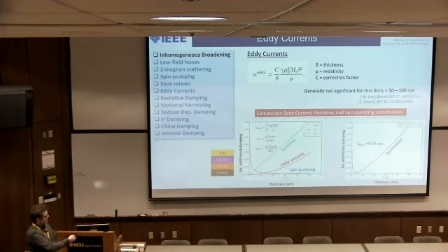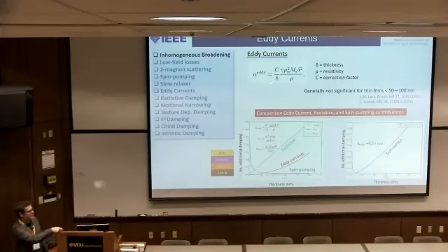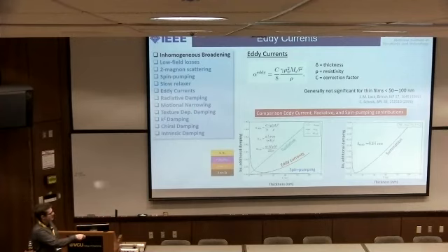And all I was saying is that, this curve, I mean, this is the equation, right? So it depends on resistivity, thickness, magnetization. That actually determines that cutoff point. For this sample, I would say maybe below 20 nanometers, you don't have to worry about it. Obviously at 100 nanometers, it's a pretty significant contribution.